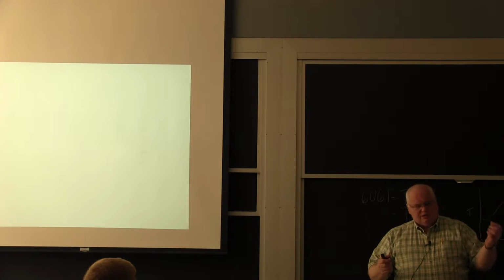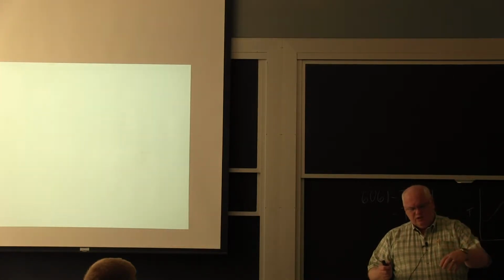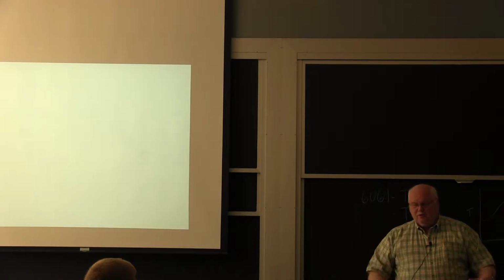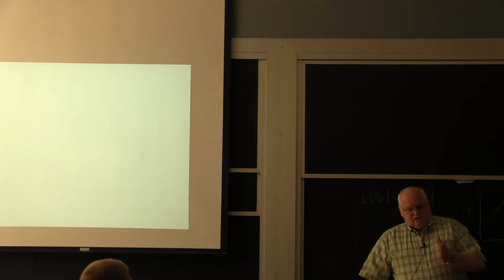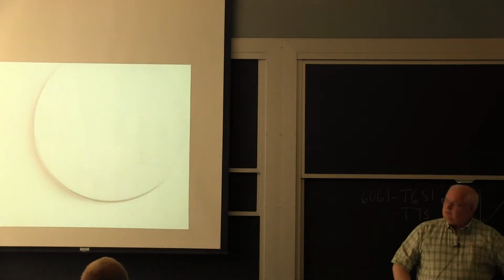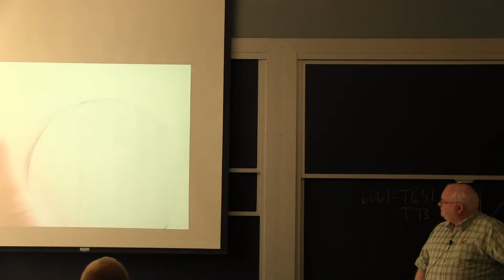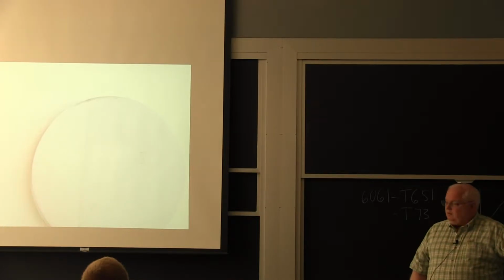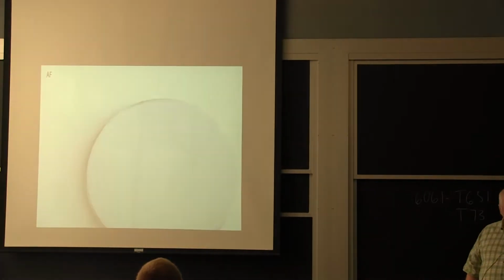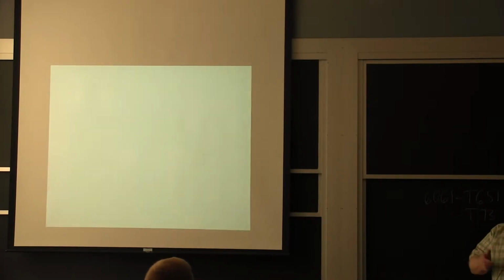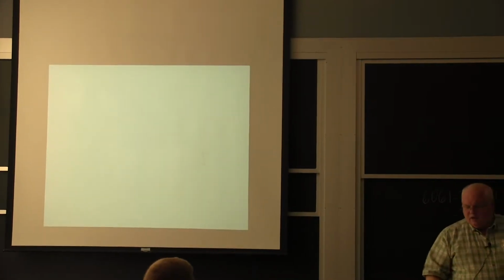Nope. It's a continuous casting process, and they pour the molten aluminum in here, one alloy, and they pour the other aluminum in here. And it turns out for aluminum, it works that the two of them just fuse together. This is actually a fairly broad fusion line. Okay. Let it focus there a little bit. I mean, you can see it's a millimeter wide. And if you got it in there, you'd see a fair amount of mixing. Okay. But they just cast together.